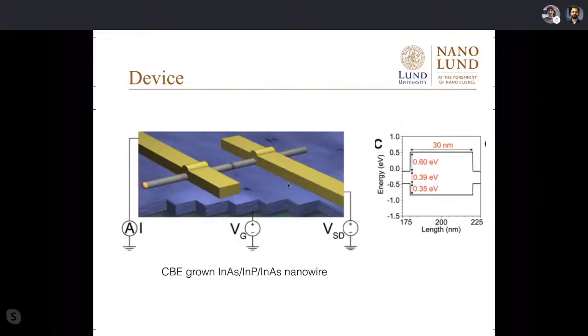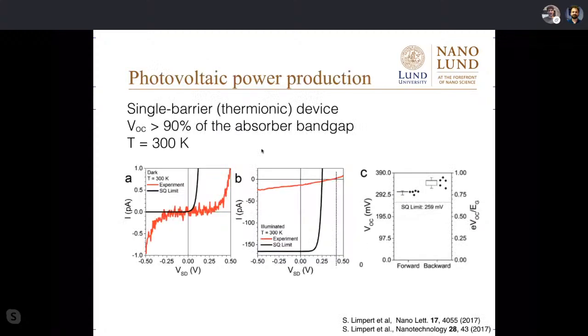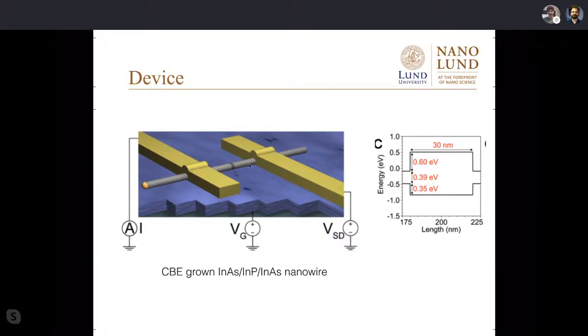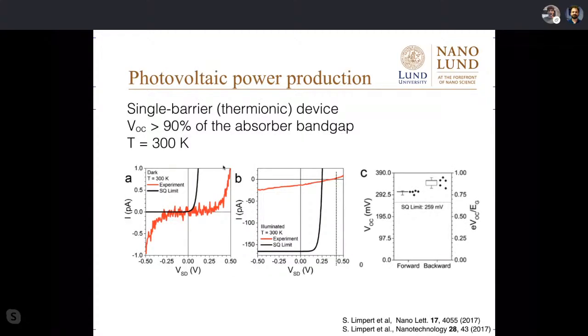And the first thing we did was to just try this without much control. So we just took a nanowire with such a barrier in the middle, slapped contacts on it, and shone light on it. And we got lucky in this case. This was maybe not supposed to work, but it did. It turns out that there's always some asymmetry. You absorb more light on one side of the barrier than on the other. This can be plasmonic effects at the contacts, or how light interacts with the nanowire. But the more commonplace, it turns out, is that you absorb by chance more light on one side of the barrier than on the other. And at first attempt, we got a solar cell to work this way.